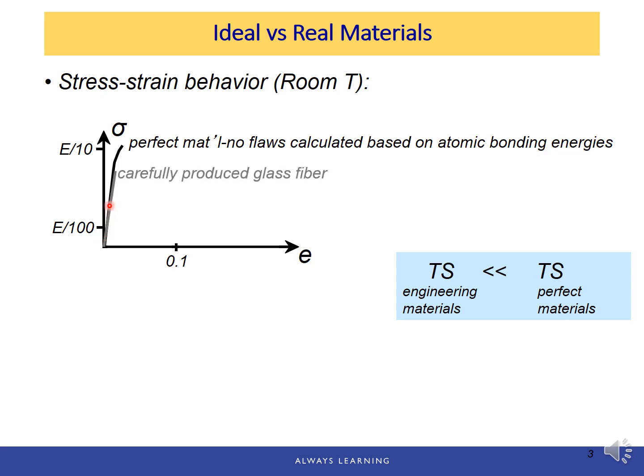Versus the real material, and this is a carefully produced glass fiber, which has a tensile strength that is lower than the ideal material. And also it's quite brittle because it doesn't have plastic deformation. And next is typical ceramic. Again, it's a brittle material, but the tensile strength is much lower than the perfect material.